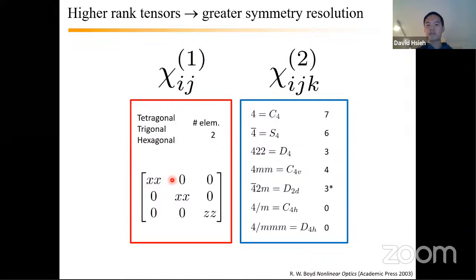On the other hand, if you go to higher rank, add one more index in this case, then not only do you gain the ability to distinguish between different crystal families, but also different point group symmetries within a single crystal class. So here I'm showing, for example, different point groups in the tetragonal crystal class. And you can see that for these different point groups, these are the number of independent elements. The tensor structure basically looks different for those different point groups. And so if you had a way to map out these tensor structures very carefully, you could do at least some point group symmetry refinement.